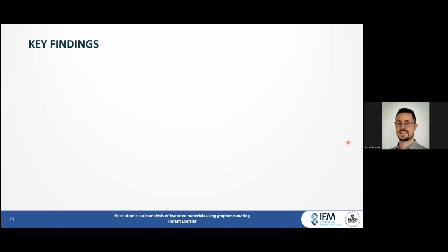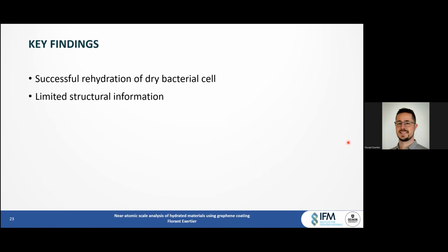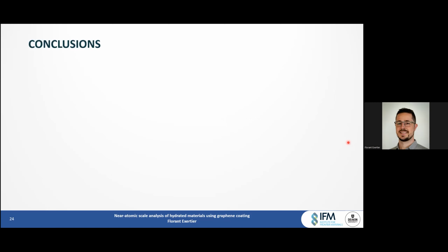So the key findings from this part of the study are the successful rehydration of a dry bacterial cell. Unfortunately we were only able to obtain limited structural information, but we were able to confirm the detection of peaks related to organic material stemming from the bacterial cell.